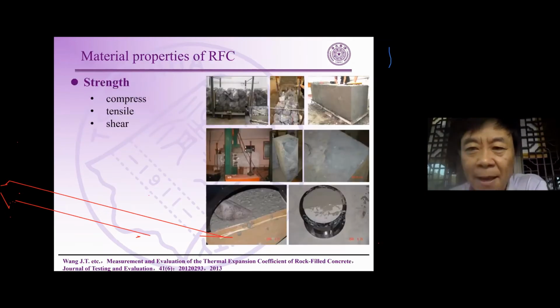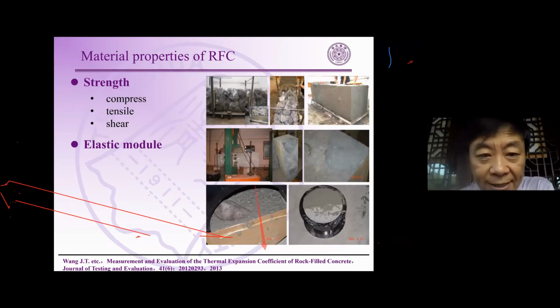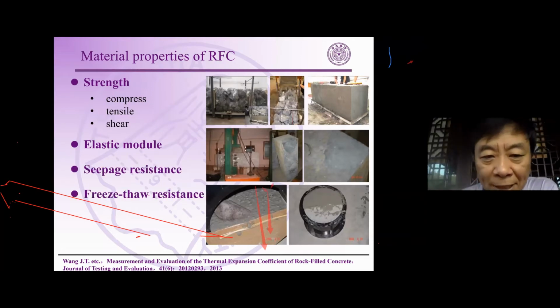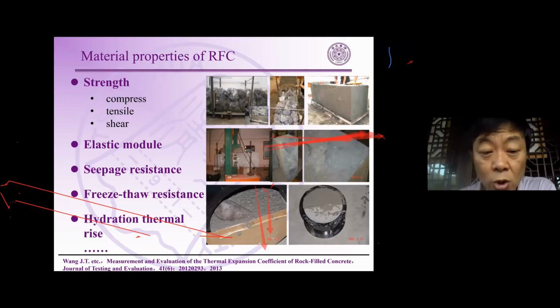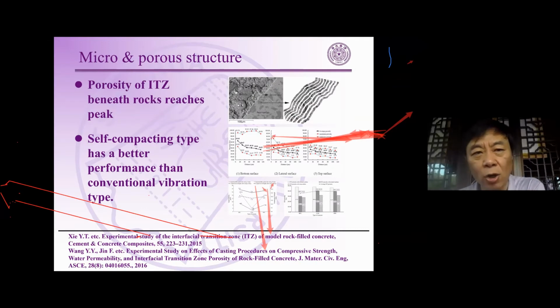And we also studied many material properties of the rock-fill concrete, such as the strength. We conducted tests of the compressive, tensile, and shear strength of the concrete. And we also tested the elastic modulus, the Poisson ratio, and the seepage resistance of the rock-fill concrete, and the freeze-thaw resistance of the self-compacting concrete. And we also tested the hydration thermal rise of RFC. And we also studied the micro porosity of the interface between the large rocks and self-compacting concrete. We use SEM to study the micro porosities of this, which we call the ITZ.